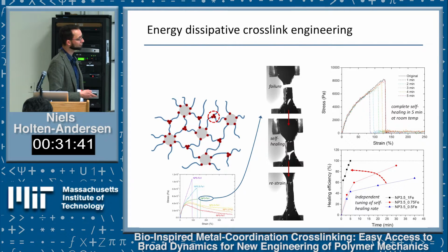Now what's even more interesting is that it's quick self-healing at room temperature. That's already exciting. But what's even more interesting is if you now begin to play with the relative ratio of metal nanoparticles and metal ions, keeping the nanoparticle loading in the material the same—giving us very solid-like properties at 3.5 weight percent particles—